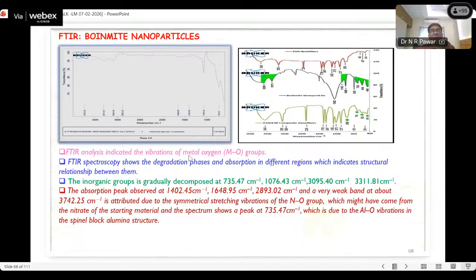FTIR analysis indicates the vibrations of the metal oxygen groups, and this spectroscopy shows the degradation phases and the absorption in different regions, which indicates a structural relationship between them. The inorganic groups gradually decompose at 735.47 centimeter inverse, and here also the absorption peaks observed are very weak bands. This is attributed to the symmetrical stretching vibrations of the nitrogen and oxygen group, which might have come from the nitrate of the starting material, and the spectrum shows a peak which is due to the aluminum and oxygen vibrations in a spinel block alumina structure.